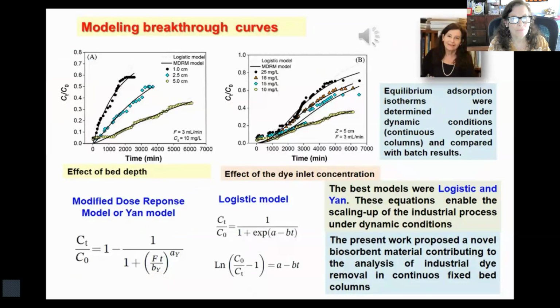The best models that fit the experimental breakthrough curves were Logistic and Yoon-Nelson. These equations enable the scaling up of the industrial process under dynamic conditions. In conclusion, the present work proposed a novel biosorbent material contributing to the analysis of industrial dye removal in continuous fixed bed columns.